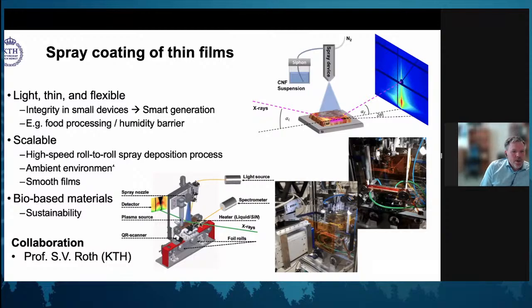We have been working a lot with trying to evaluate what happens in films. And to the top right, I will get back to that a little bit later. We're trying to show that we are using a CNF suspension. In this case, we are spraying. What we have is a spray, spraying a nanocellulose film, and then we're using something called grazing incidence with X-rays. You can study the behavior of the film.